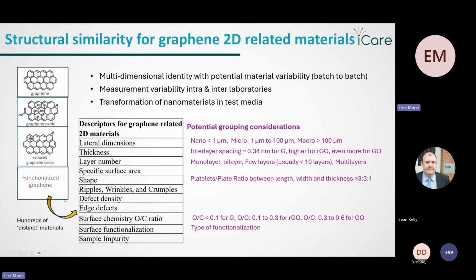So, as it was mentioned earlier, we need multiple descriptors for graphene related to the material identification. There are hundreds of more or less distinct materials that can be classified under 4 categories: graphene, graphene oxide, reduced graphene oxide, and functionalized graphene. And within those categories, we have potential for material variability, and there are some other uncertainty aspects that can be linked to measurement variability. And as with most nanomaterials, they are quite subject to extrinsic properties transformation. But if we stick to primary, intrinsic descriptors, we can already have some potential grouping considerations regarding those 4 categories and, a bit within the categories, the subcategories.